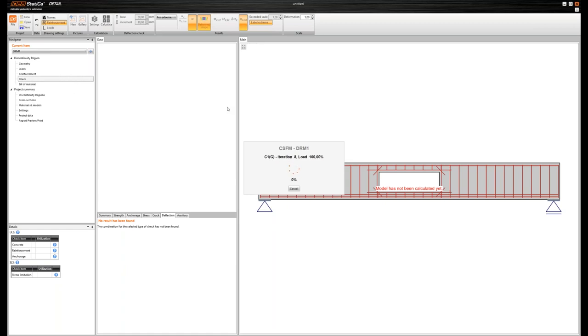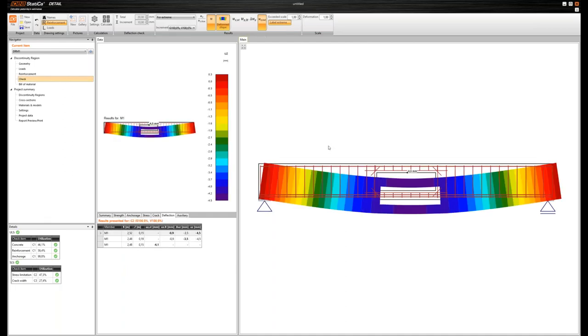So firstly, I have increased the amount of reinforcement that was failing. Second, I have added reinforcement around the opening. The software returns to the previous view where we can see the overall displacement. One thing to note here is that the displacement dropped from 9 mils to minus 4.5, which means that I have reduced the displacement by 50% just by adding reinforcement,